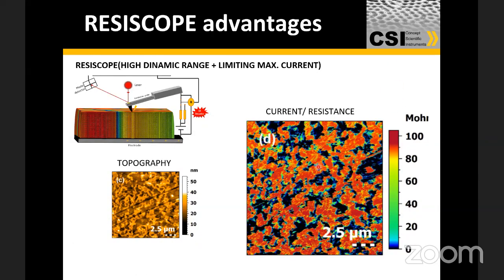So you see the color coding scale here? What this is telling you is that the spots that are red are at a higher, draw a higher current. Wait a minute, is it the other way around? Because this is gold. Essentially, since this is in megaohms, reddish colors are higher in resistance and bluish are low. More conducting surfaces are bluish, and insulating surfaces are reddish. That's what I was trying to clarify, because the substrate is gold, so the darker regions are of higher conductivity and the brighter regions are of higher resistance. Is that clear now? Yes, it's clear. Thank you, sir.